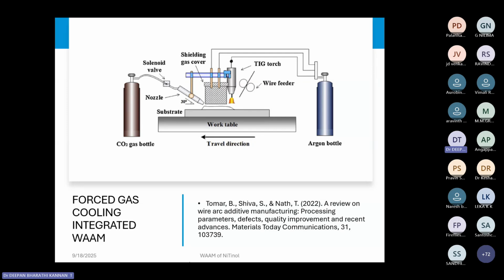So we need to identify at what interlayer temperature the next layer has to be built. If we are doing it immediately, the molten metal gets disturbed, the flow of the molten metal will get affected. If you are cooling it, if you're allowing it to cool for a long time, and then you're depositing the next layer, the adhesion between the two consecutive layers may get compromised. So we need to find the correct interlayer temperature such that the adhesion between each layer is on the higher side.